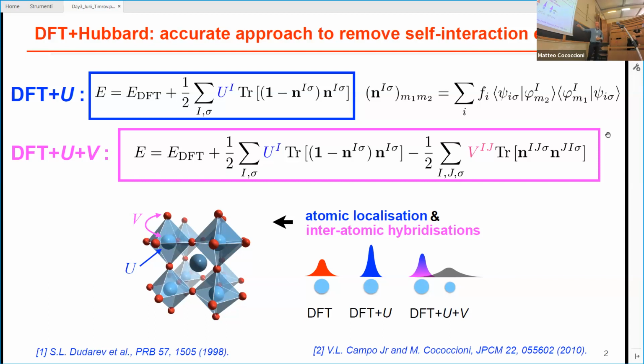So we can do whatever we want, but I want to keep it there. If I use atomic orbitals and just U, I would push too much, and as I increase U, to 10 eV and until infinity, in the limit I will go to the sharp case, and I will kill that. That is wrong. So that means I need to put plus V to somehow restore this covalency.